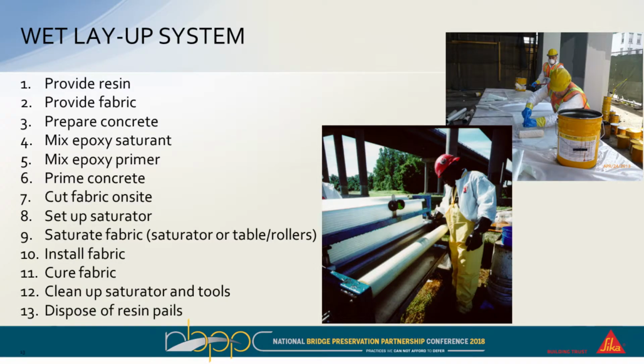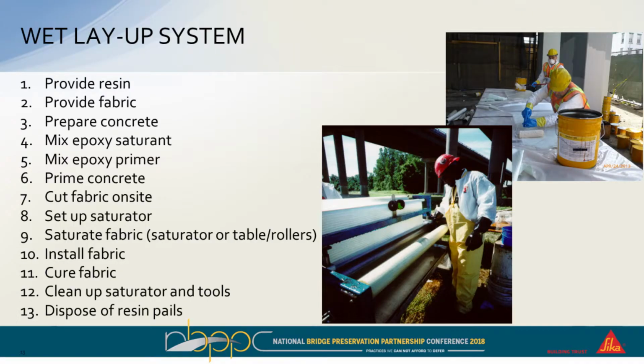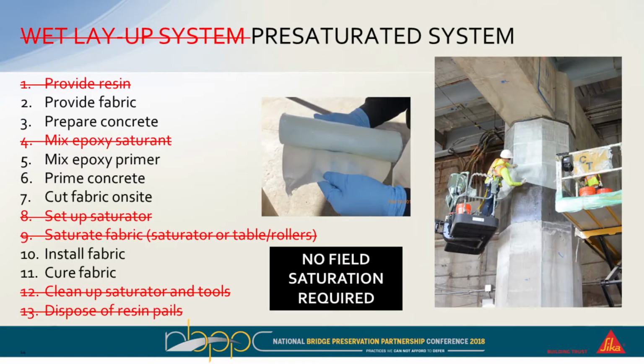So here's the typical steps that take place in a wet layup system, and it's a very linear progression, multiple steps, and you really have to make sure the contractor gets trained and goes through all these steps, from providing the resin and mixing and saturating and cutting the fabrics. I'm not going to go through everything, but the point here is there's a lot of steps that have to take place, and if you cheat on one step, that can compromise the entire system.